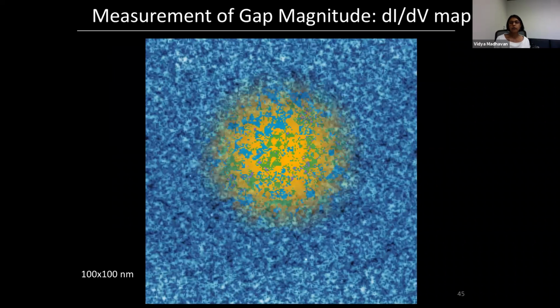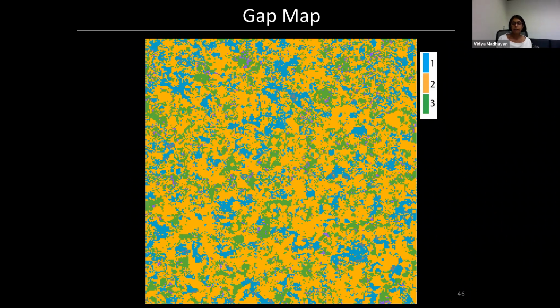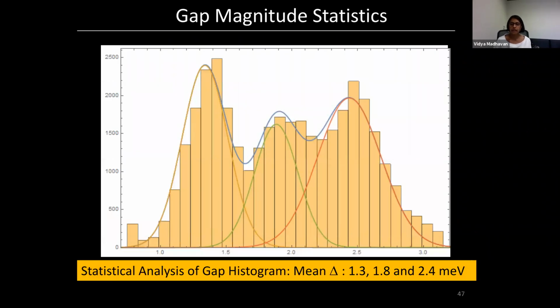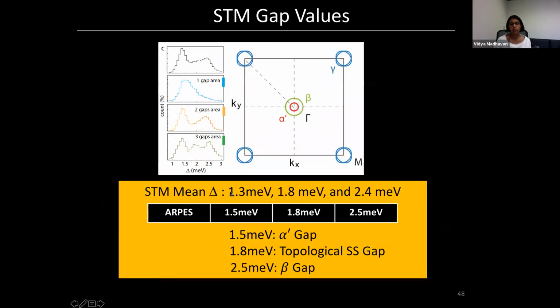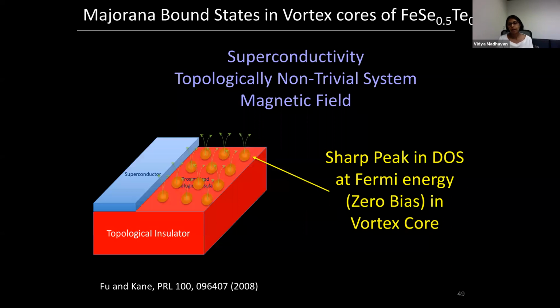So we can go in and do a statistical analysis of all the gaps that we measure. This is the analysis. So from these histograms, we can get the mean values of 1.3, 1.8, and 2.4 millivolts. And the important thing is that these numbers match very well with previous measurements of the gaps. And the other important thing is we see this 1.8 millivolt gap, which is actually associated with this topological surface state. Okay, so now we have all the ingredients that we need to see Majorana fermions.